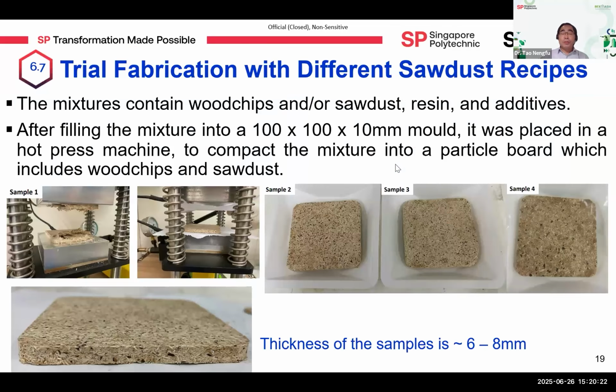As various wood chip and sawdust sizes may lead to homogeneity issues in the mixture and in turn affect the strength of the particle boards, trial mixing has also been conducted after sieving the as-received wood waste. The mixture contained wood chips and sawdust, resin and additives. After filling the mixture into a 100 by 100 by 10 mm mold, it was placed in a hot press machine to compact the mixture into a particle board.